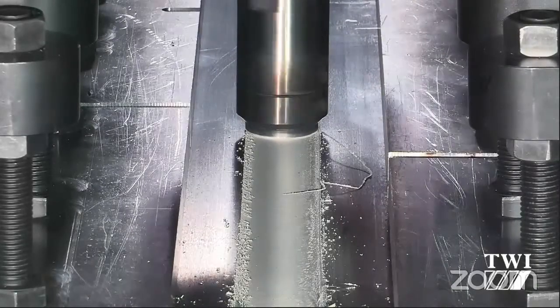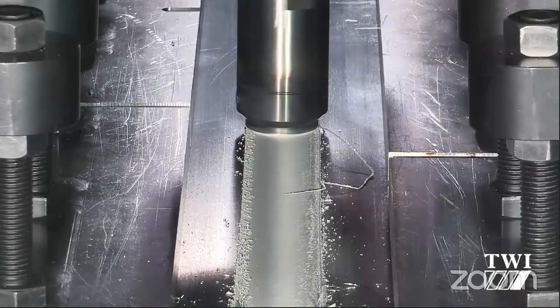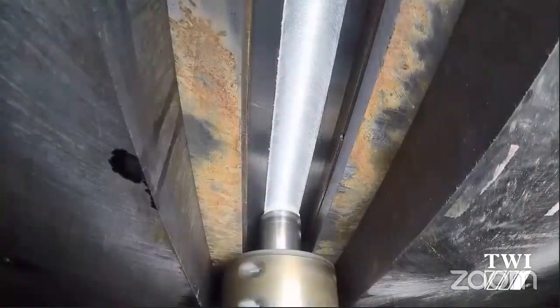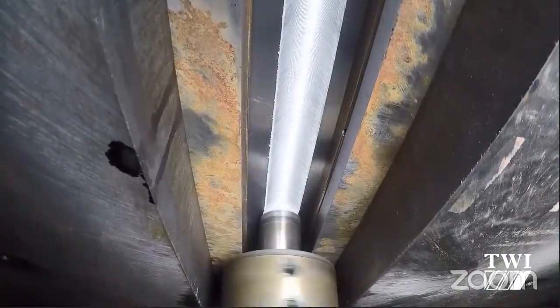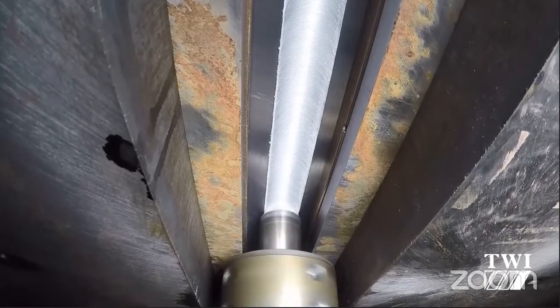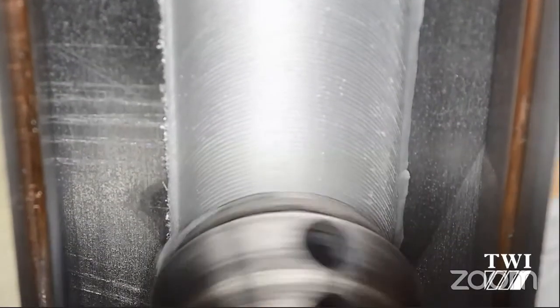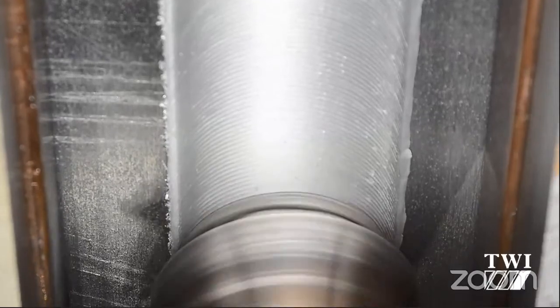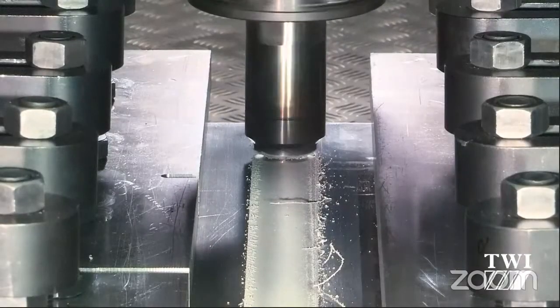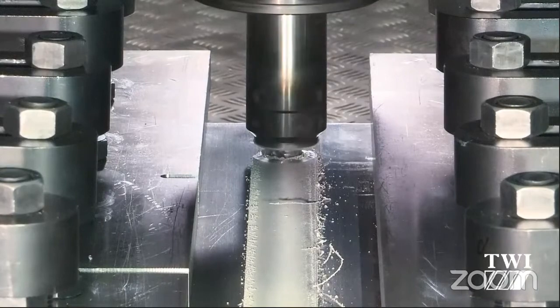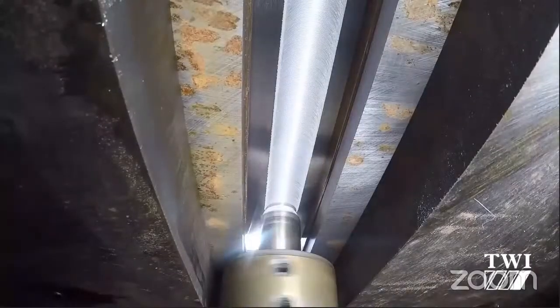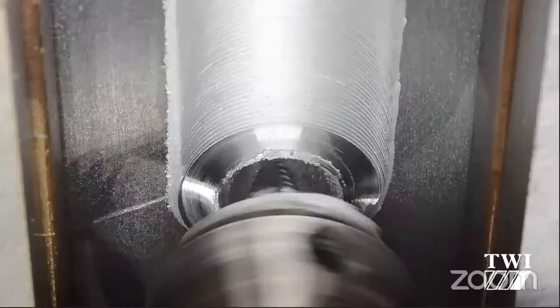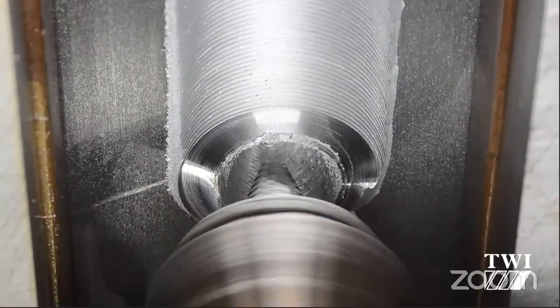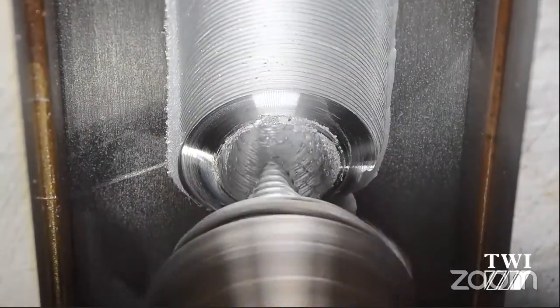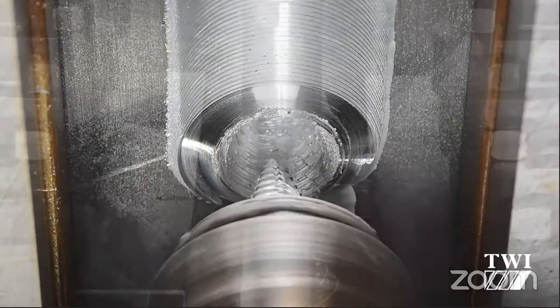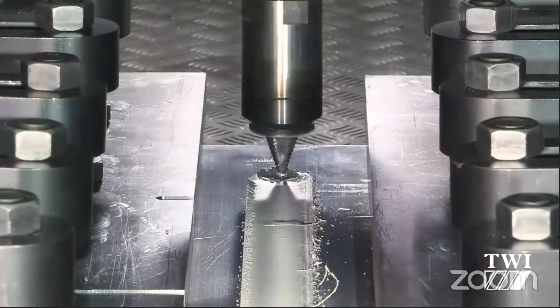As you see, we don't get any fumes, we don't get any sparks, we don't get any ultraviolet. We get a very nice smooth surface finish to the weld. In many applications, it's not necessary to do any post-weld dressing because the surface is good enough to put straight into service. And then at the end of the weld, we simply extract the tool. So realistically, it's very similar to milling, gives an extremely strong bond, it's completely mechanized, and gives very good results.